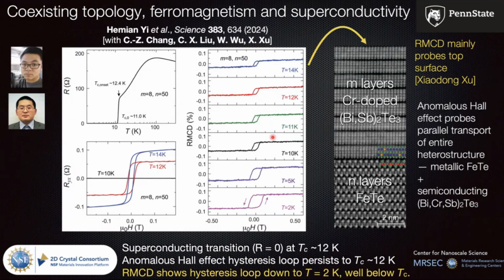So he grew these samples where he grew bismuth antimony telluride doped with chromium under the conditions where if you simply grow it on strontium titanate, you would get the quantized anomalous Hall effect. But instead, he grows it on this iron telluride. And indeed, at temperatures above 10 Kelvin, you can see an anomalous Hall effect. Now, of course, it's not quantized because there's a metal underneath, that's shorting and all that. But interestingly, if you lower your temperature further, you then get a transition to a superconductor.